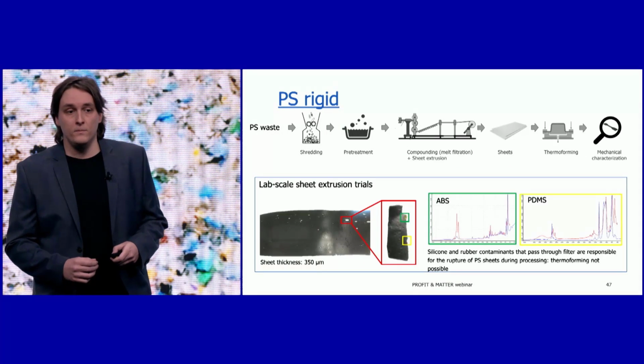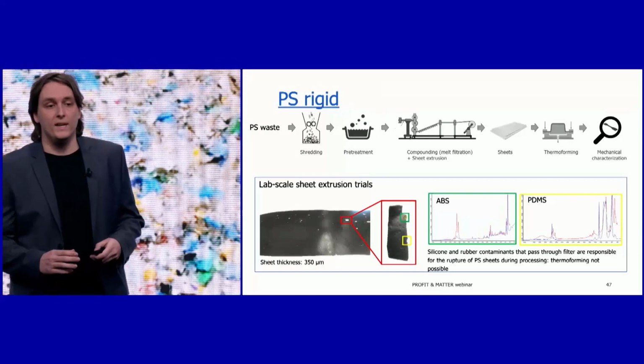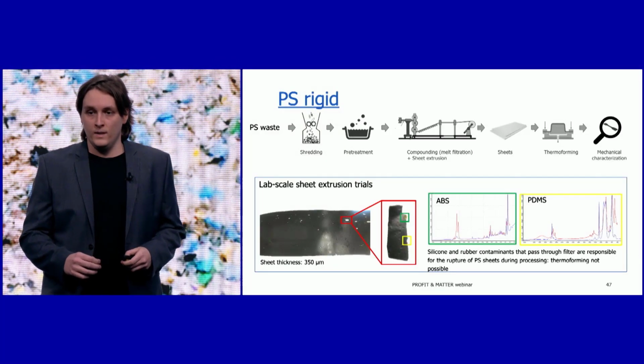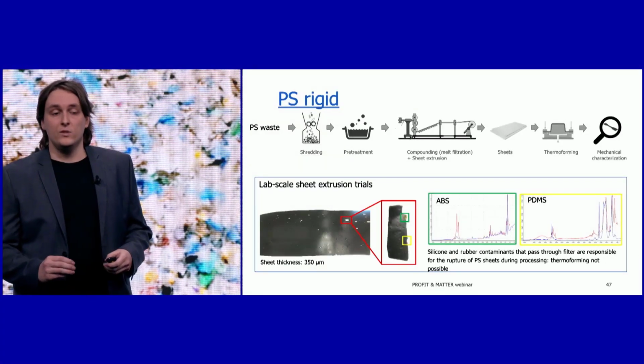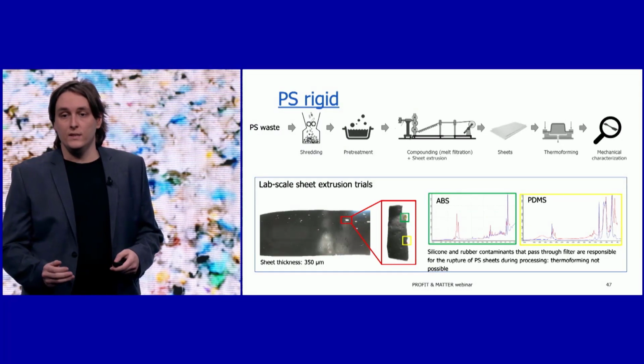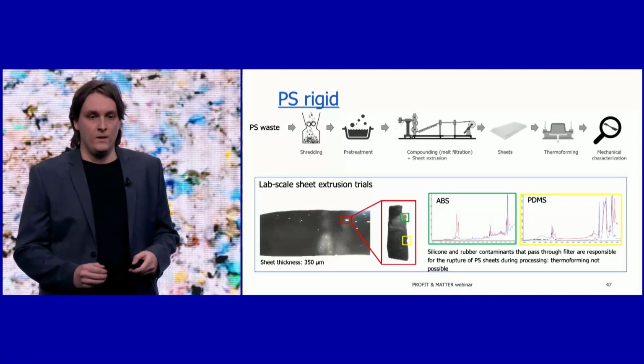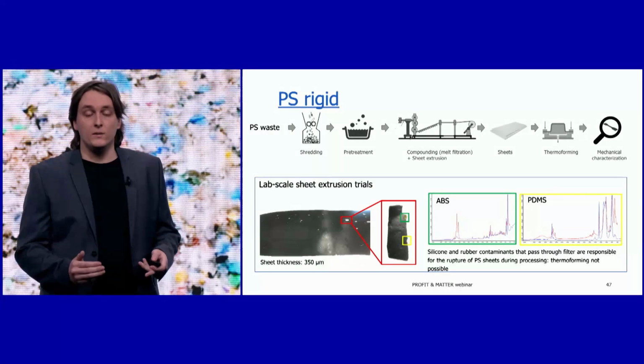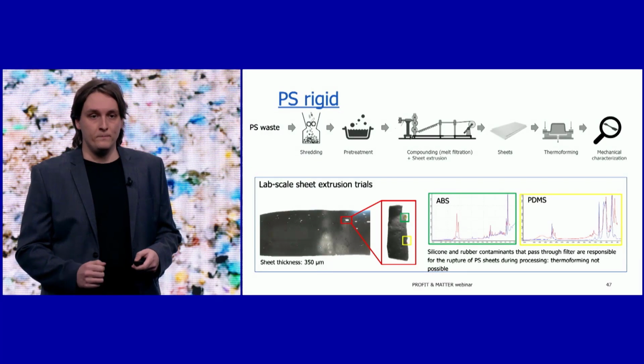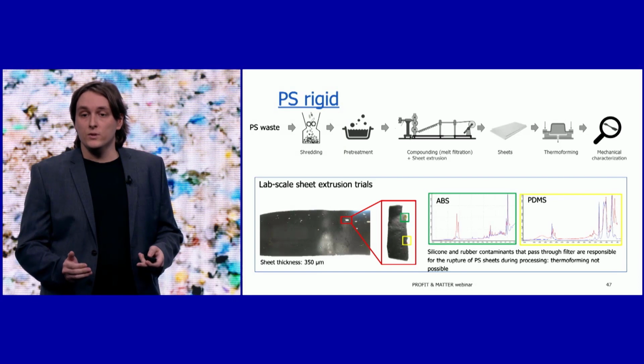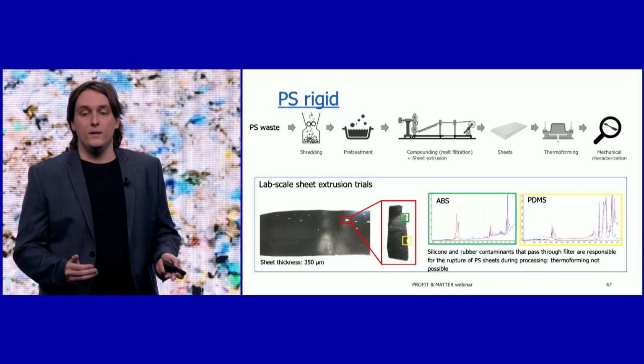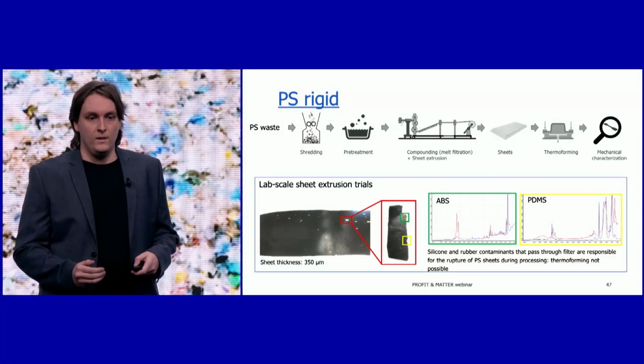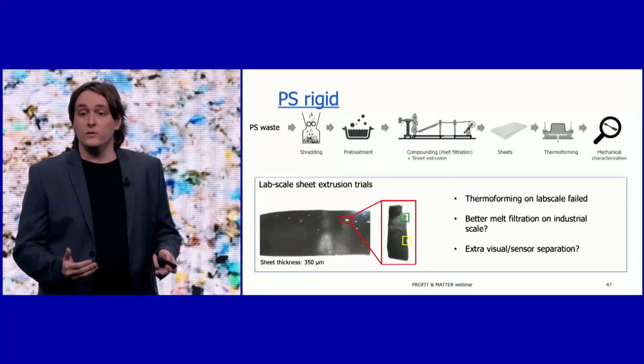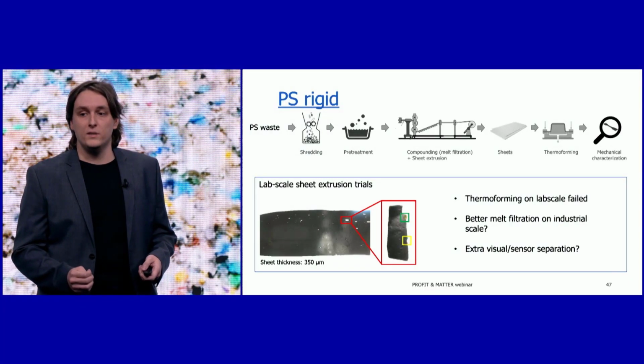A second stream on which we tried mechanical recycling was a PS rigid stream. This PS waste was shredded, washed, and then extruded into sheets for thermoforming. On lab scale, it became clear that other polymers were contaminating the waste stream, and those rubber-like components caused rupture in the polymer sheets during thermoforming and extrusion. So the lab scale testing failed for thermoforming of the PS sheet material.